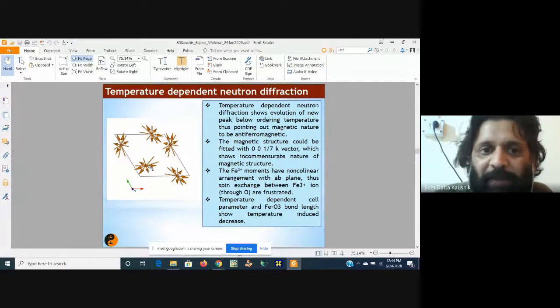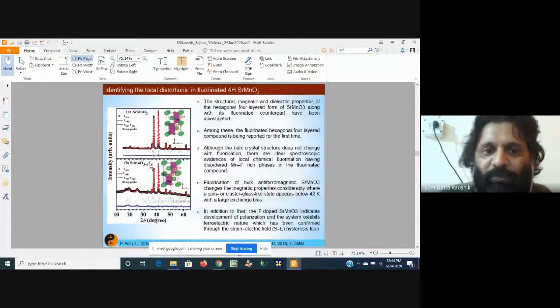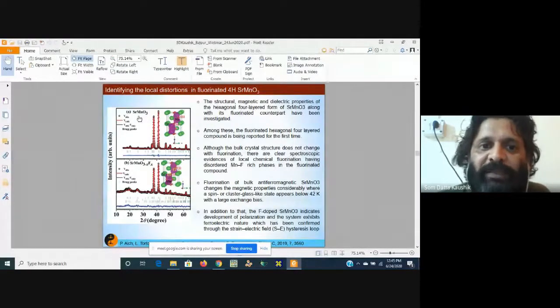Since time is less, I will quickly go through some more examples, and then we can conclude and have some questions. This is another study, on an SrMnO3 sample, in which we forced fluorine to go to the oxygen site. But how do we identify whether the fluorine has gone to the oxygen site or not? We carried out neutron diffraction at room temperature. We can clearly see a difference coming up at low angle. By analyzing this, we could identify that fluorine can go to the oxygen site.